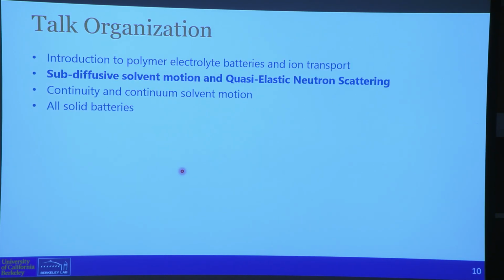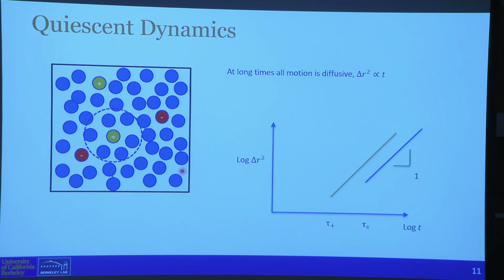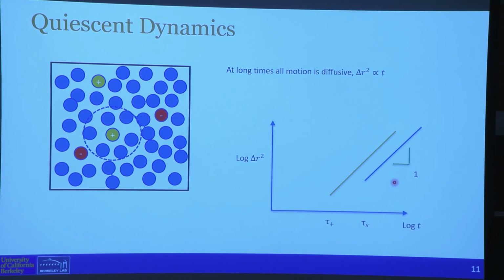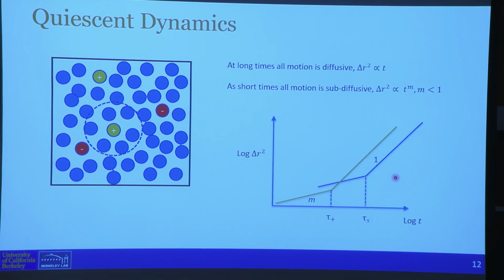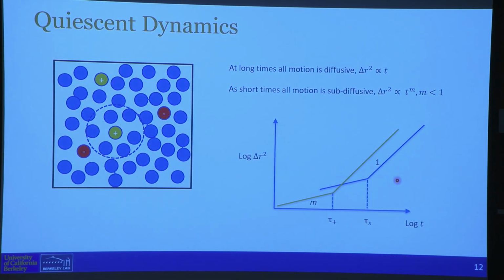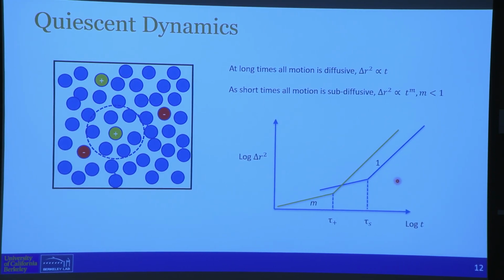All right, we're ready to move on to the next topic, which is subdiffusive motion and quasi-elastic neutron scattering. You have an ion, you have a solvent, and they're all jiggling around randomly, Brownian motion. And at long time, Brownian motion, the mean square displacement goes linearly with time. So if you were to take a particle, whichever one, and you plot it, the slope of log delta r squared versus time would be 1. That's just Brownian motion. But at small times, the mean square displacement would be a little less than 1 going with time.